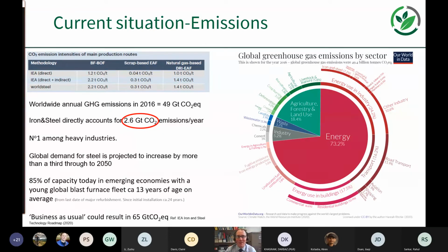As you'd imagine, there's a variety of different scales and efficiencies of plant around the world. But basically what we're emphasizing is that the blast furnace has a higher specific intensity. So we're around a couple of tons of CO2 per ton of hot metal. Then the directly reduced iron, which might go into an electric arc furnace, is less. And then the lowest of the current technologies which are adopted is the scrap-based electric arc furnace. So it's quite a considerable difference there at 0.3 tons CO2 per ton of hot metal out of that furnace.